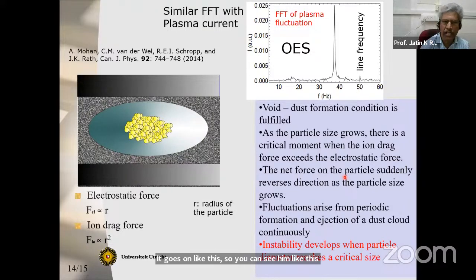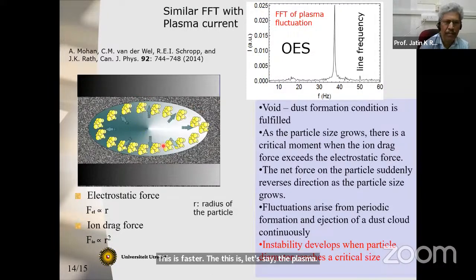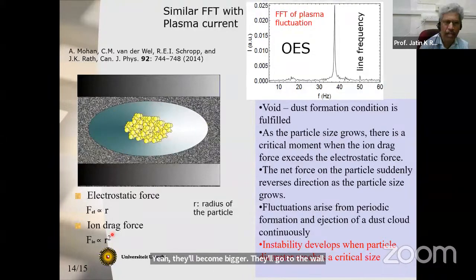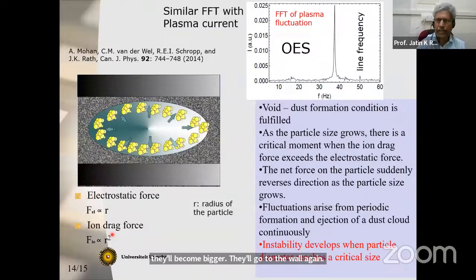So you can see it like this. This is, let's say, the plasma zone. These are the two walls. In the plasma zone, first the particles are formed. Then at some time the particle size becomes bigger because of the R square. They become bigger and they go to the wall. Again, new particles will form. Again, they go to the wall. So it goes with a frequency.